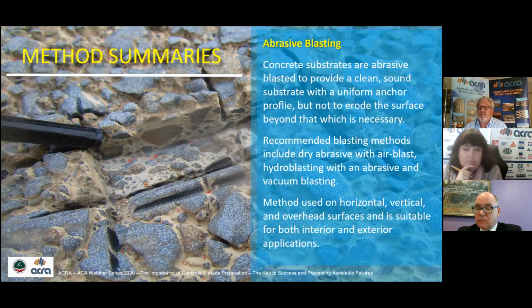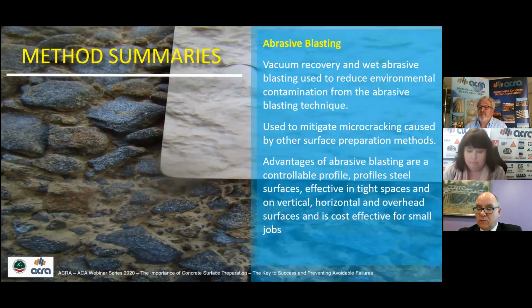Recommended blasting methods: we can do dry abrasive with air blast. We can do hydroblasting with an abrasive with an airless. Hydroblasting with abrasive and water, and airless centrifugal wheel blast. Vacuum blasting is another alternative. The method can be used horizontal, vertical, overhead, and is suitable for interior and exterior applications. Both vacuum recovery and wet abrasive blasting equipment are sometimes used to reduce environmental contamination. Abrasive blasting is often used to mitigate micro cracking caused in the concrete surface through other methods.